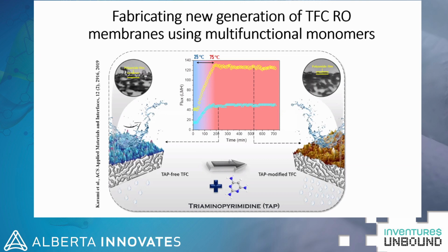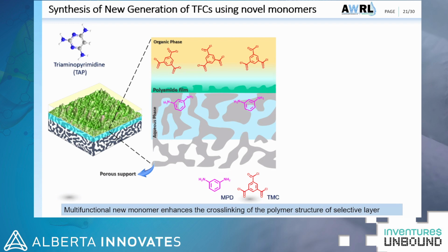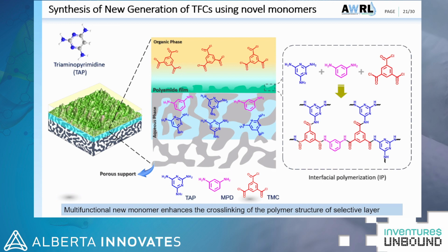So in the water phase, we had two monomers, not just one monomer, which is MPD, which is commonly used by membrane manufacturers to make RO membranes. We added another monomer, which is TAP here, a multifunctional monomer. And in the organic phase, we had one monomer, TMC. And the IP reaction has led to the formation of a new generation of polyamide on top of the porous support, which is more cross-linked.